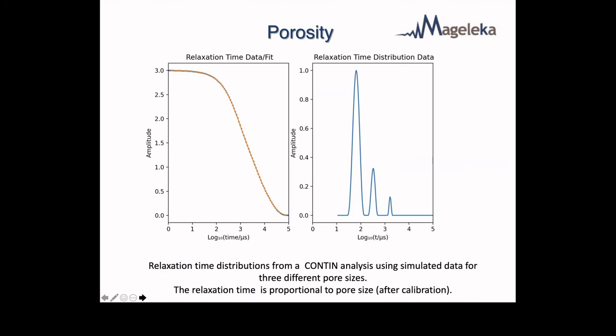And in fact, some of you who are familiar with light scattering will know about the CONTIN analysis used in DLS for deconvoluting multiple correlation functions. Well, it turns out you can use exactly the same analysis procedure with NMR relaxation times. So in a typical NMR experiment, we might have 16,000 data points. So you can see that it makes this type of deconvolution really useful. In DLS, of course, you never get that number of data points. And so we can use the CONTIN analysis and dig out.